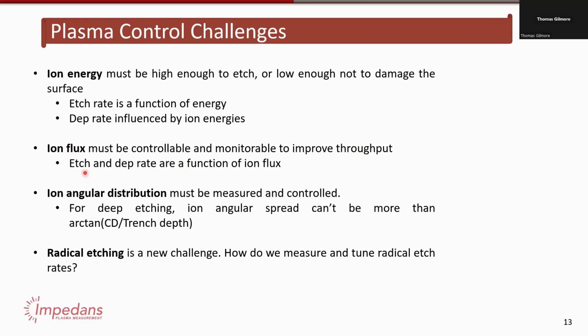So this is the next challenge. The two that are kind of newer are, we need to have more information about the ion angular distribution. If we're doing these deep etching, high aspect ratio things, the ion angular spread, I'm just going to give a number here, can't be more than this: the arctan of the critical dimension divided by the trench depth. In other words, if you have a trench which is 100 to 1 aspect ratio, or 200 to 1, or 400 to 1, this would be the arctan of 1 over that number. This gives you the ion angular spread which is allowed.